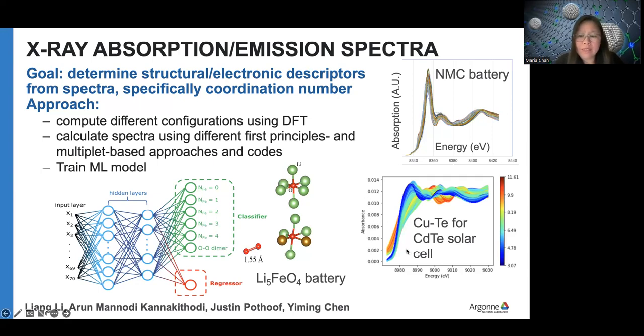In another case yet, we looked at a dopant in a semiconductor solar cell material, cadmium telluride. X-ray absorption really shines in these kinds of situations because the dopants are there in parts per million or even less sometimes. Other techniques would completely not be able to see it, but because X-ray absorption is sensitive to a specific element, we can pick out dopants such as copper and arsenic in cadmium telluride, even when there are very small amounts of them.